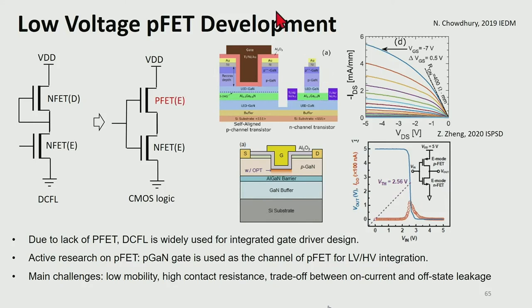So if you see this right figure, by using the p-GaN region of the gate stack in the conventional E-mode power device, a low voltage PFET was fabricated. To push the VT, a recessed gate structure was used, and to increase the threshold voltage further, undoped gallium nitride or some plasma treatments were applied. And as you can see in the right figures, decent device performance and initial inverter operation were successfully demonstrated.